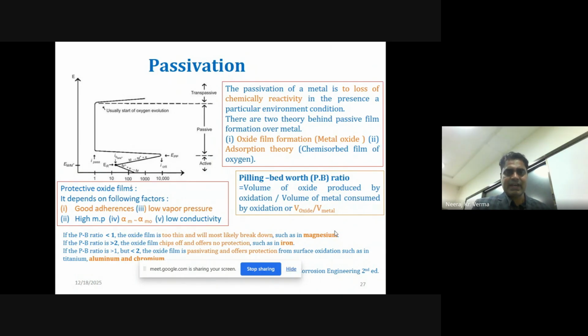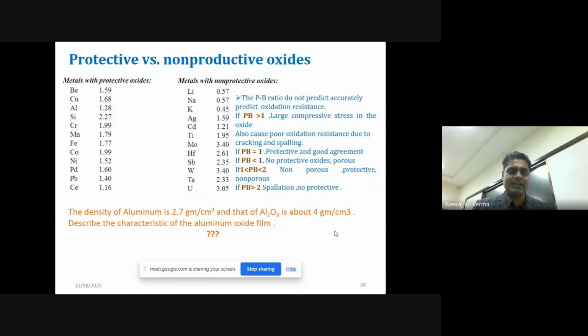So passivation is nothing but the formation of oxides, and if you supply a high amount of potential to the system, it starts to propagate again. That region is known as the transpassive region, right? We calculate these things with the help of the Pilling-Bedworth ratio. It is the volume of oxide produced by the system divided by the volume of metal consumed by the system. So this PB ratio is responsible for protective and non-protective behavior, that is, passivated and not passivated. We can see several examples here.